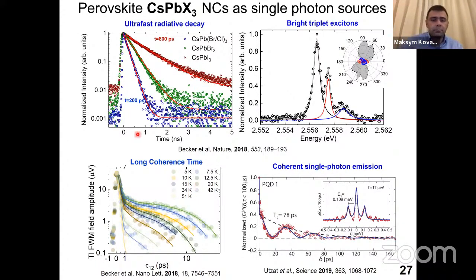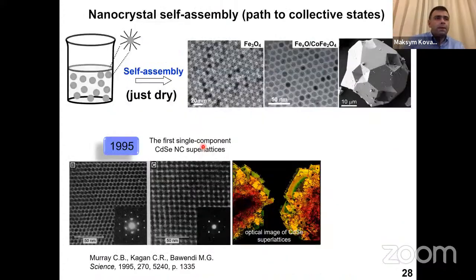And so here again, we look at the history where people have used drying-mediated self-assembly of nanocrystals to generate long-range ordered superlattices. You simply can take a monodispersed colloid of nanocrystals of spherical shape. You can dry out the solvent, and you will end up with a superlattice. This is known for cadmium selenide for several decades now.